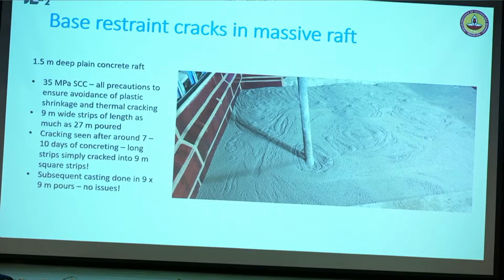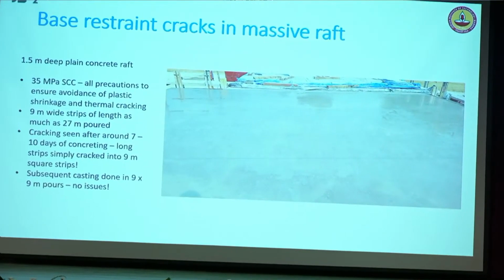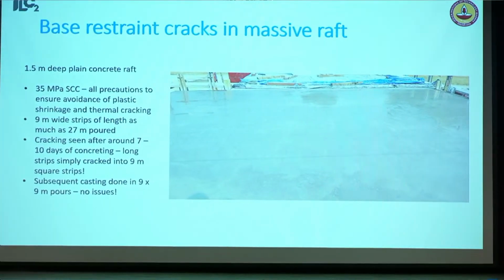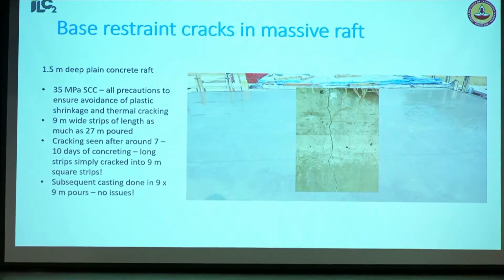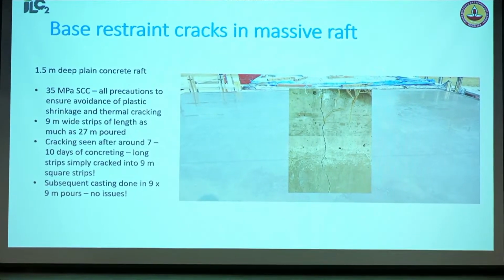So this is again showing you the top surface perfectly. No cracking. All the possible precautions were taken. And this is the cracking that actually appeared because of the base restraint.